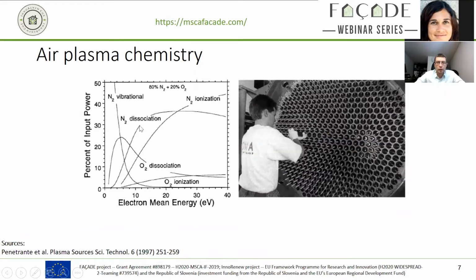Generally, for these kind of plasma discharges, I said they're very energy efficient. And the reason, just as one detail on the side, is the gas phase chemistry. So we are exciting, particularly if we're using air as a process gas, very efficiently with the energy that you're providing. That's typically in this region around or slightly below 10 electron volts. We are very efficient to excite the nitrogen that's in the air, and this electronic excitation of nitrogen can then only be relieved again through interaction with other gas species.